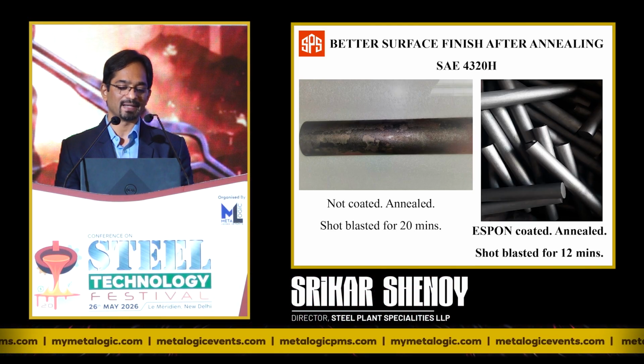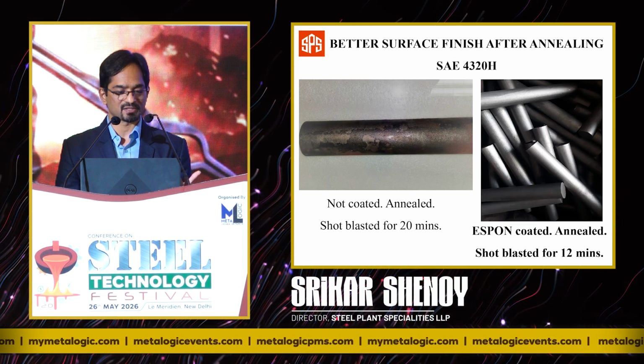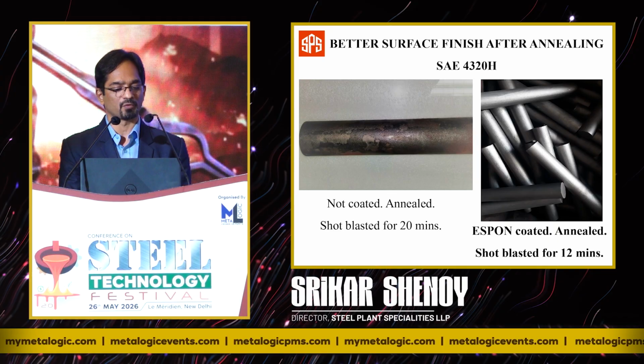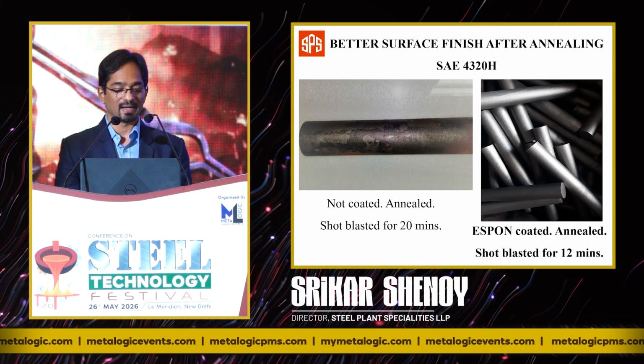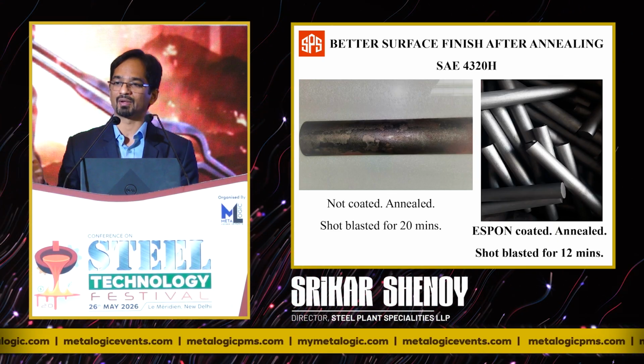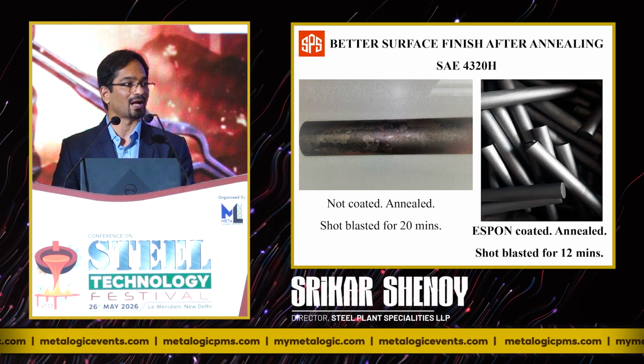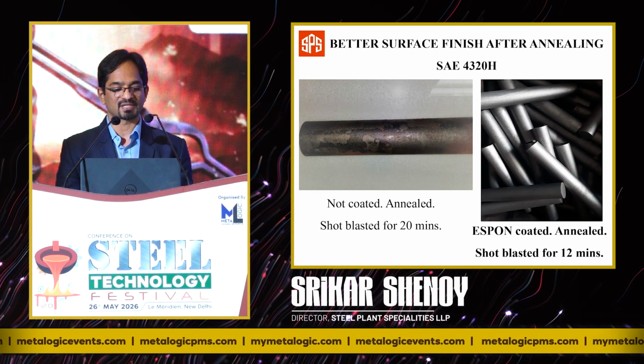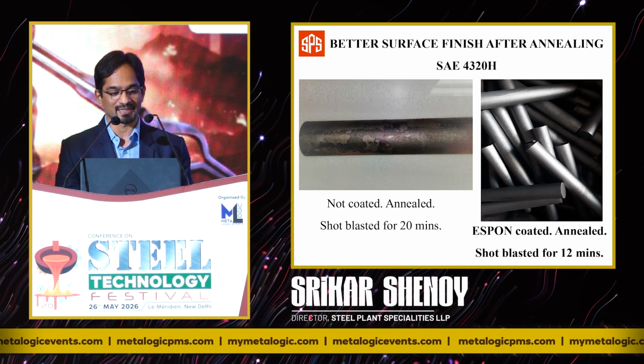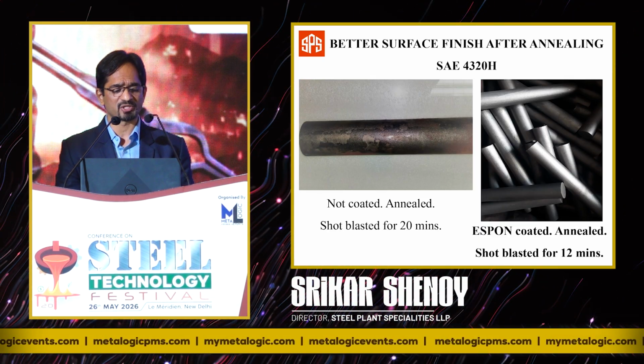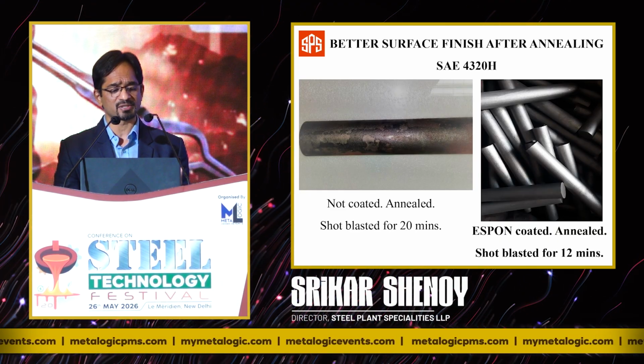These are hot rolled billets. They are spheroidized annealed prior to cold forging, and spheroidized annealing is a very long heat treatment cycle lasting for 16 to 18 hours. And what happens after such prolonged heating is what you're seeing on the screen. A lot of blemishes. In spite of shot blasting, there are still scale pits here.